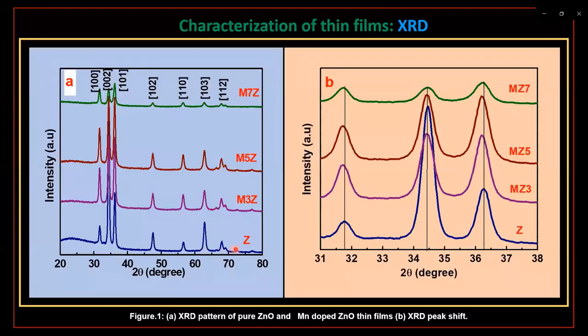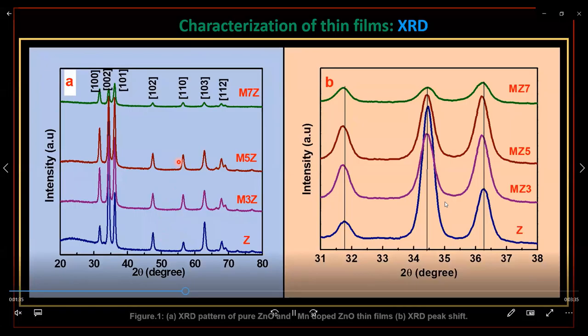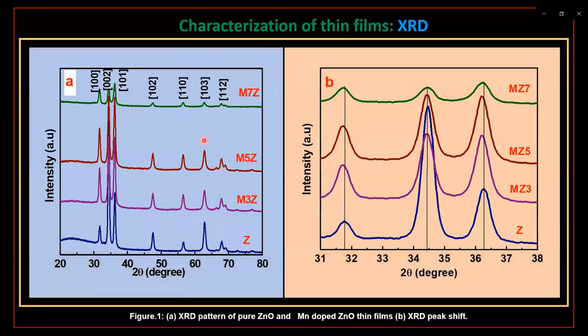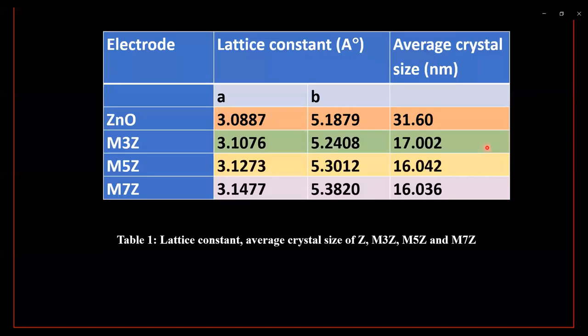The first figure shows the XRD pattern of pure ZnO and Mn-doped ZnO. All peaks indicate the formation of a high purity hexagonal ZnO wurtzite crystal structure. There are no extra peaks due to Mn metal or other oxides. It is a single phase, and Mn2+ might have substituted the Zn site without change in crystal structure. Figure B confirms the shifting of the predominant peaks toward a lower angle as Mn concentration increases.